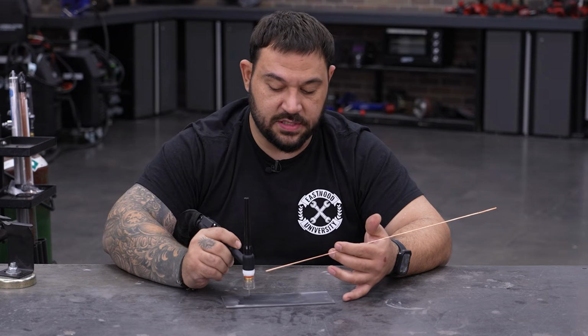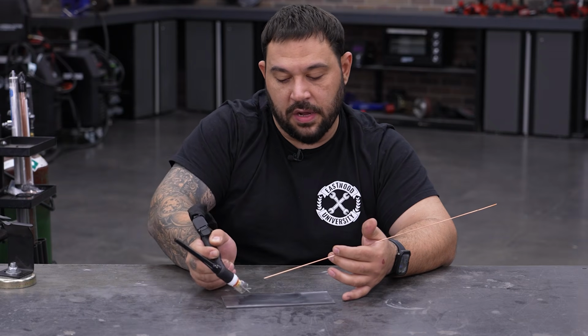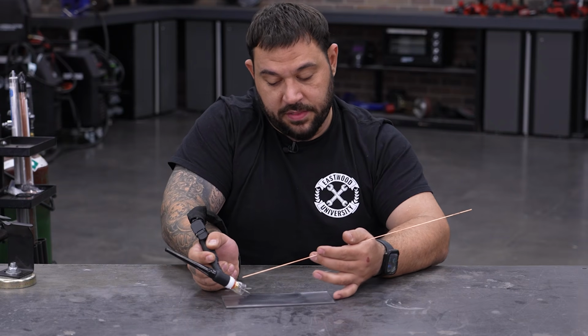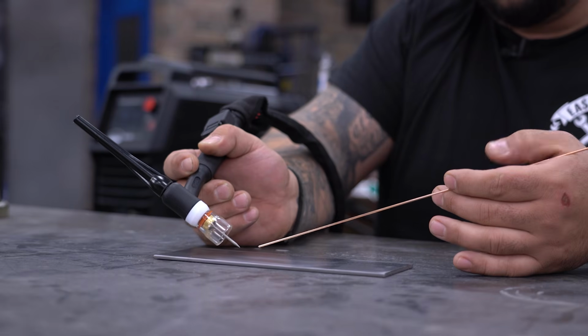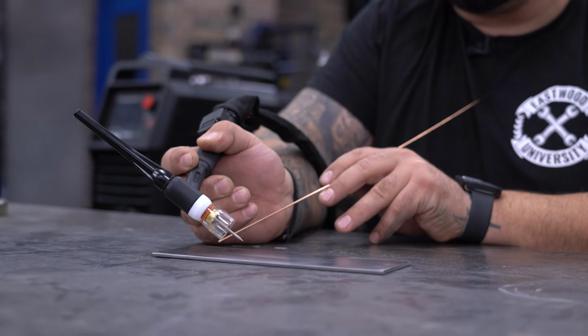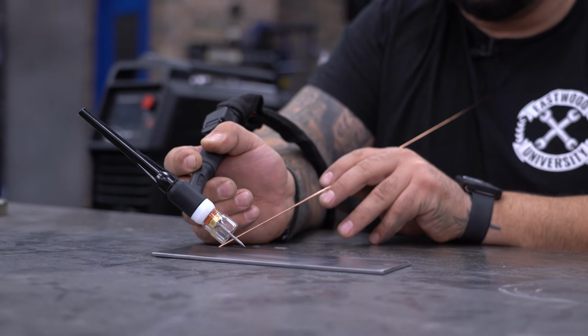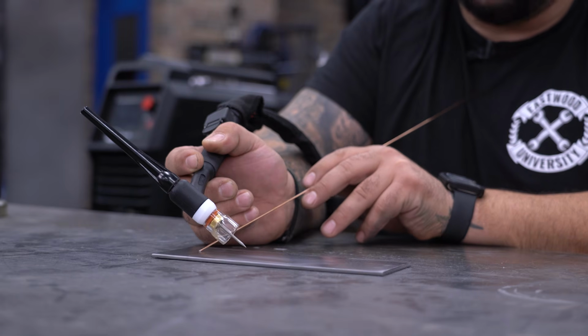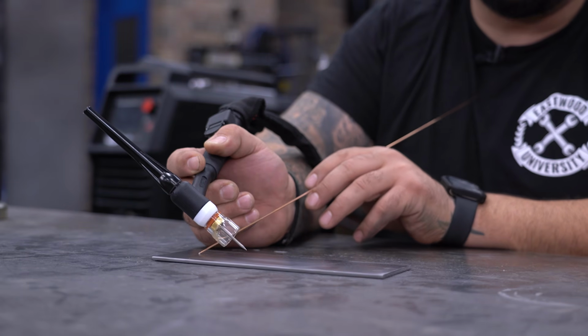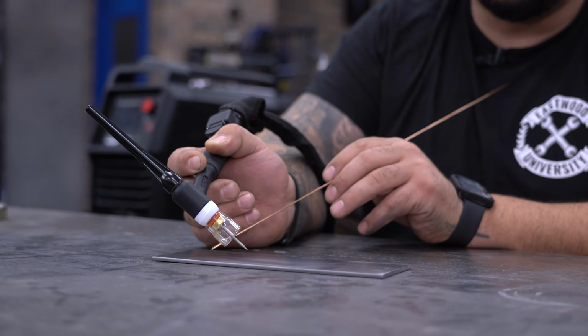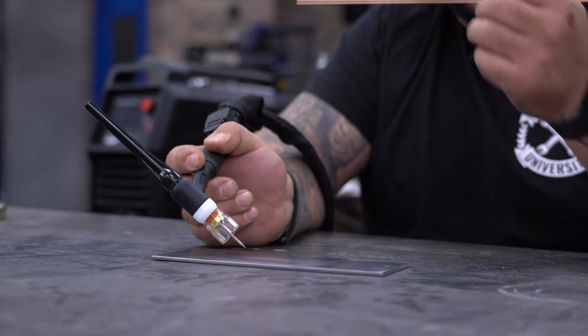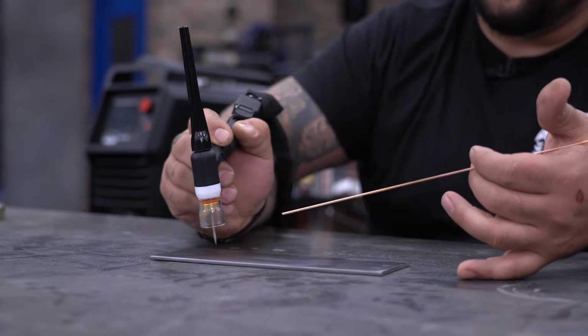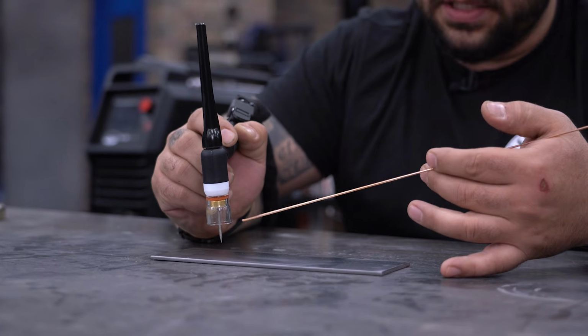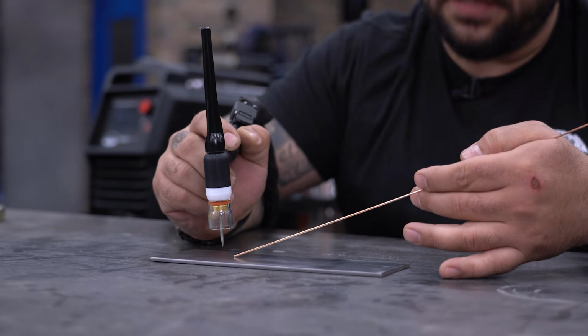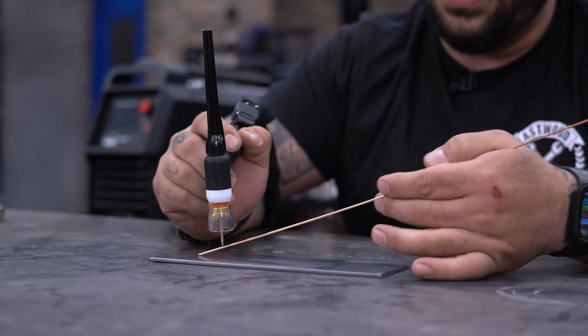Now, the reason that this is important is if I start to create a really harsh angle with my torch as I'm pushing along here, once the back side of my nozzle clears that weld, any weld bead behind my nozzle is no longer getting the shielding gas that it needs. So it's going to oxidize before the rest of the weld. So one thing we want to try to do while we're TIG welding is keep our torch as straight as possible. This way, when we get our shielding gas to make contact with our weld, we're getting an even dispersion behind and in front.